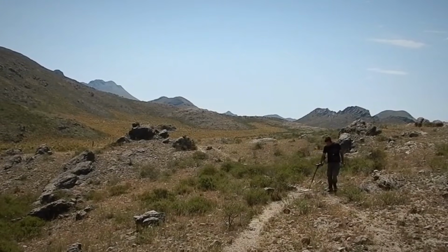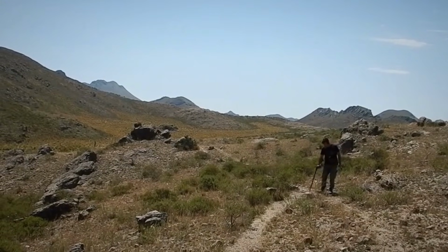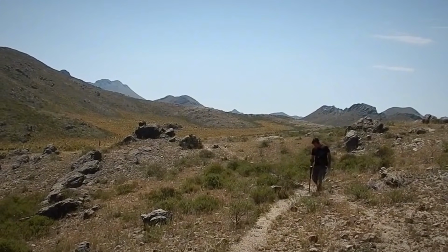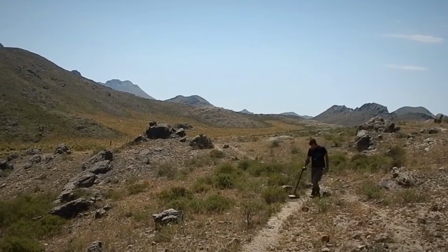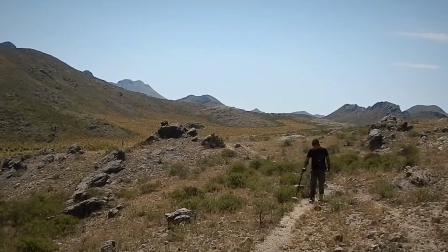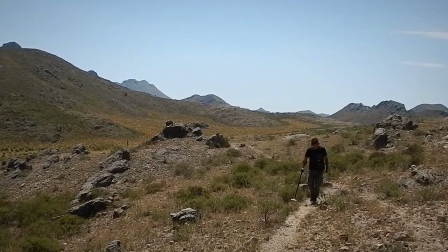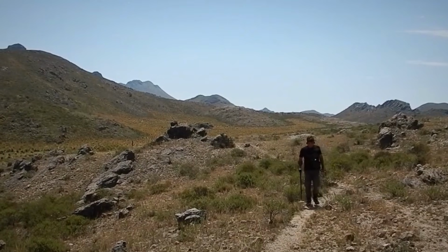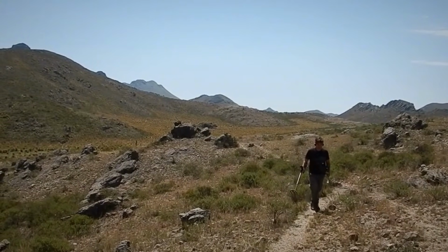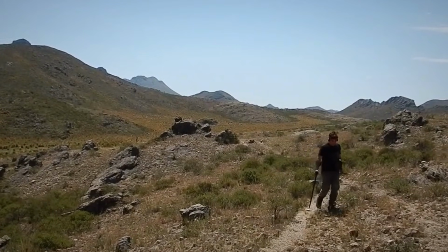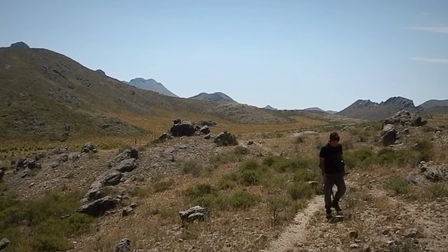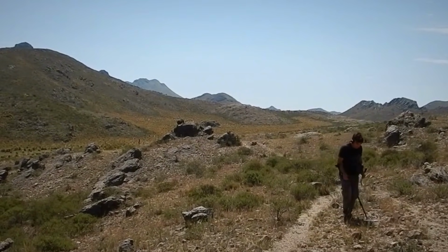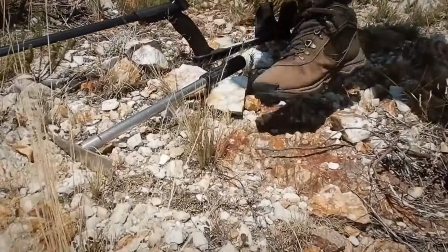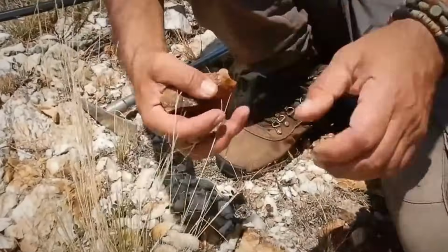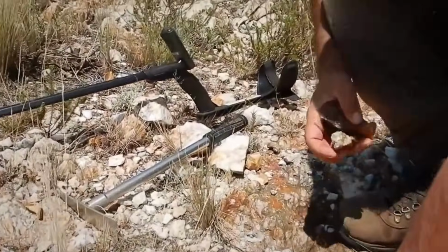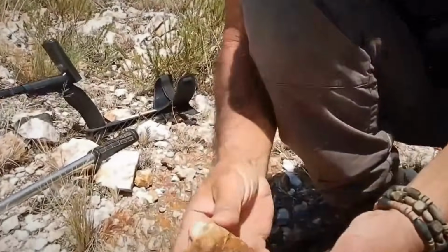Free milling gold, loose and recoverable with gravity separation, is only part of the story. In some systems, the bulk of the value lies locked within sulfide minerals, invisible to the naked eye and inaccessible without roasting, flotation, or chemical leaching. And in this case, early signs pointed toward exactly that scenario. After crushing and panning 3 key samples from the vein, the weight of visible gold was underwhelming, barely 0.2 grams in the best case. Yet the surrounding quartz was rich in sulfides, especially pyrite and minor chalcopyrite. This mismatch raised a red flag. If visible recovery was low but sulfide presence was high, the likelihood of refractory gold, gold embedded within or chemically bound to sulfides, had to be considered.